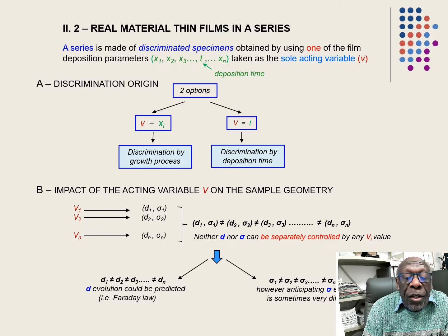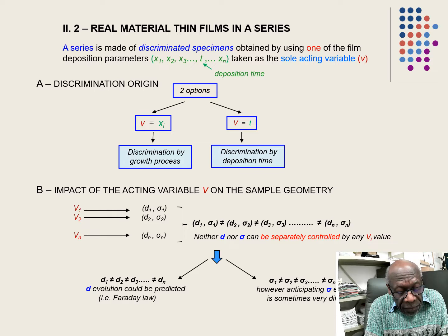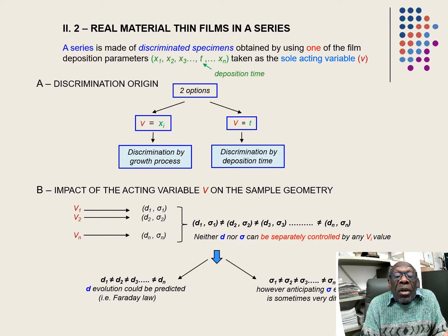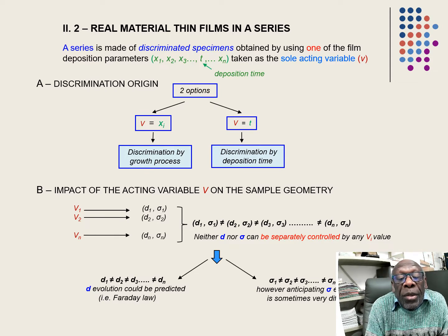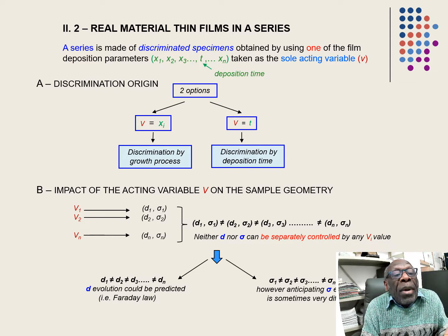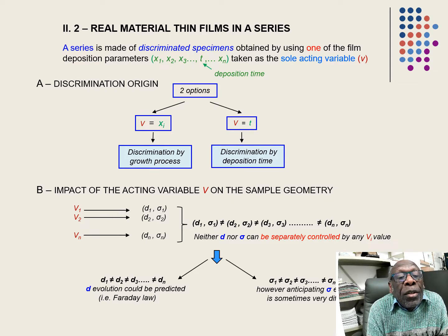For doing science in general, if you want to study the evolution of film properties, in practice, we used to use a series of specimens, but discriminated specimens. There are, I can say, two options to discriminate the specimens of your series: by growth process, as proposed here, or by deposition time. Whatever selected option,